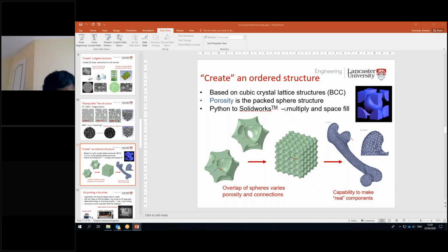And as we've seen in other studies as well, it's quite a popular approach. I'm picking up really on the packing of things like BCC structures, which you see in the black and blue model. The packed structure becomes the inverse, and that becomes the porosity in these models. And we can tailor the overlap of the spheres in that packed structure to vary the degree of porosity and interconnection. And by using Python or similar coding coupled with CAD packages like SolidWorks or SpaceClaim, we can then multiply these structures up, and we can even do space filling as well. So on the right-hand side, there's an example of an arbitrary image, in this case of a bone, and that's filled with a series of these inverted BCC elements.